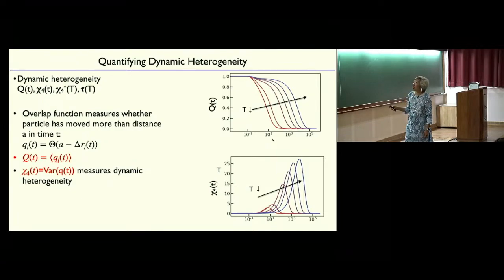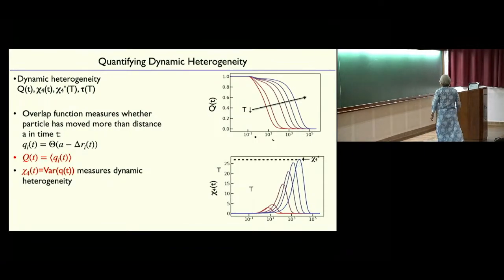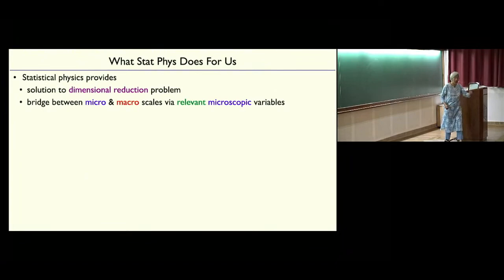But you don't have to just look at the average. You can also look at the variance of this overlap, and that's what measures the dynamic heterogeneity. If you look at the variance, it has a peak. That peak occurs at the relaxation time for that temperature. I'm not going to go into details about this, but the peak height measures the degree of heterogeneity in the system, so chi4 star. That's the way you quantify it. I'll come back to that.